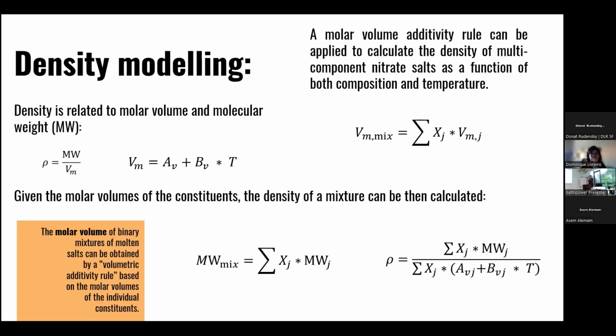So according to the scientific literature, we tried this approach starting from the molar volume of each component. And so starting from the molar volume, we can calculate the molar volume of the mixtures as a function of the composition and temperature. I reported only some formulas just to give you an idea. Density is related to the molar volume and to the molecular weight. So given this experimental data that we obtained during the campaign, the density of the mixture can be calculated with this formula.